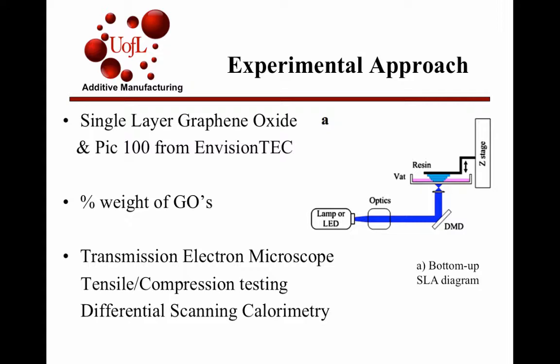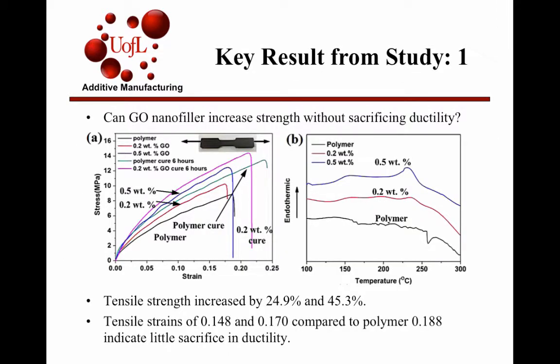So, study 1, the main gist of the study was, can the nanofiller increase the strength without sacrificing ductility? And they did see a significant increase in strength. As you can see here, we have the 2 graphene oxide polymer peaks, and those are a lot higher than the polymer without the graphene molecules. And then what they did to take it even a step further is they cured the 0.2 weight percent graphene oxide for 6 hours in heat, and it actually increased the properties even more and gave it more strength. And that's the top curve you see here.